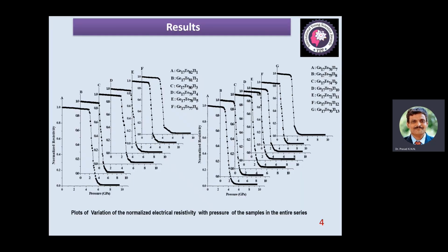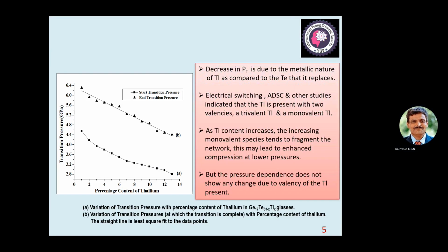Now moving on to the next part, where we wanted to know how this sample family behaves, where you could see there are 13 samples obtained just by varying the thallium content as a percentage. If you look at A, B, C, D, E, F in the graphs, there is a variation in thallium content: Tl1, Tl2, Tl3, Tl4, and so on, up to Tl13. So about 13 samples in the entire series have been taken by varying the thallium content. Then we plotted a graph of variation of electrical resistivity with respect to pressure for the entire series. We noticed the following results. We plotted a graph by taking percentage content of thallium along the x-axis and the transition pressure along the y-axis, and then we could notice the following points.